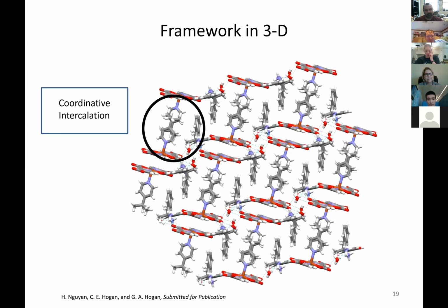All right, so again, we saw the possibilities now within our 2 papers that we have more examples of the coordinative intercalation with the pyridines, kind of what we expected because of the basicity of pyridine itself. Looked like there was a driving mechanism because of the groups that we chose onto the pyridine itself, forced its way to give us the coordinative intercalation. So that's pretty much the gist of those 2 papers that we had that has come out recently.